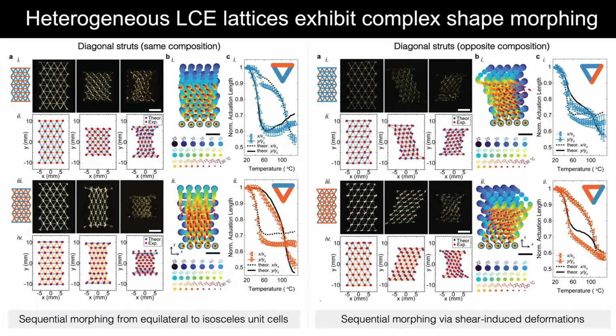transforms. And then when the struts are opposite in composition, where you have a high and a low, or a low and a high and a low, that's when things get a little frustrating, because one strut diagonally wants to shape morph earlier than the other one. And then we get a sequential morphing that's evolved by a shear-induced transformation.